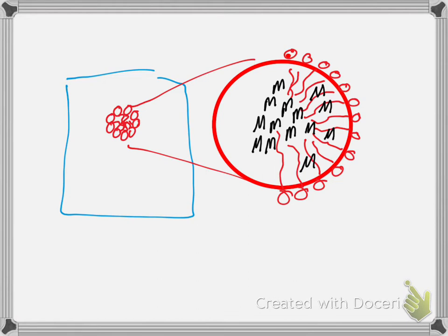So, if we take a look at this micelle, what we've got is the micelle itself, the circle, the hydrophilic heads at the outside, the hydrophobic tails pointing in. Monomer can migrate into those, in between those tails, because monomers are, by and large, hydrophobic. All that has to happen now is our initiator coming in there and starting off the polymerization.